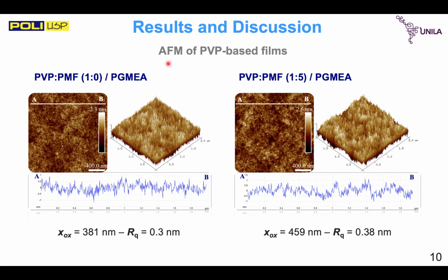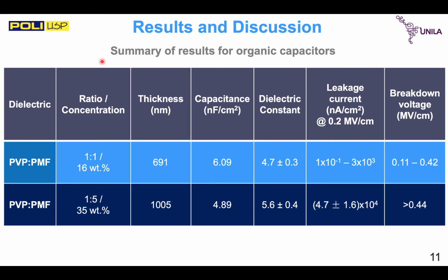Atomic force microscopy is important in order to assess the roughness of the surface. In this case, pure PVP films had a roughness of around 0.3 nanometers, while after PMF addition, the roughness was also around 0.3, a little bit higher, but not higher than 0.4 nanometers for similar thicknesses. After showing that the device had gone through cross-linking and the roughness was low, we fabricated some capacitors.